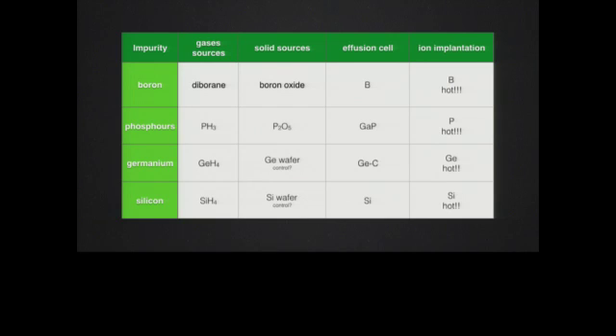We can also use solid sources. The problem with the phosphorus solid source is it tends to stay around for a long time. We can also use gaseous sources like diborane for boron, and also germane and silane for silicon and germanium. And people have also done ion implantation. The key there is that you do hot ion implantation. You do it into a hot substrate, at about 500 degrees C, so that you get some recovery even during the implantation process.